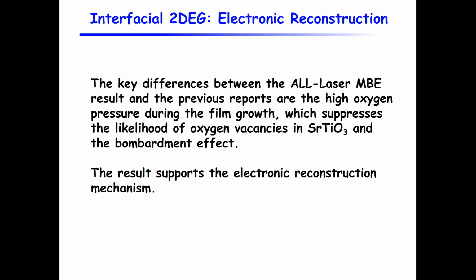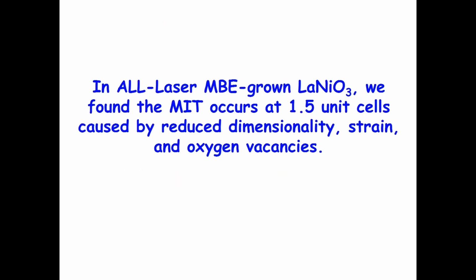Again, if you ask why other people don't get it and you get it, I will say that the key difference is that we are able to grow at this high oxygen pressure, which suppresses oxygen vacancies and the bombardment effect, and we are able to grow them still layer by layer. Nobody else could grow with the conventional PLD or laser MBE. And I think this supports the ideas of electronic reconstruction.